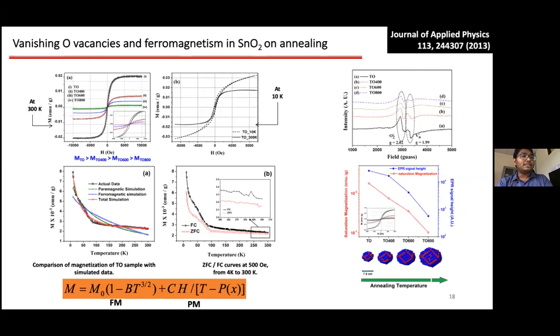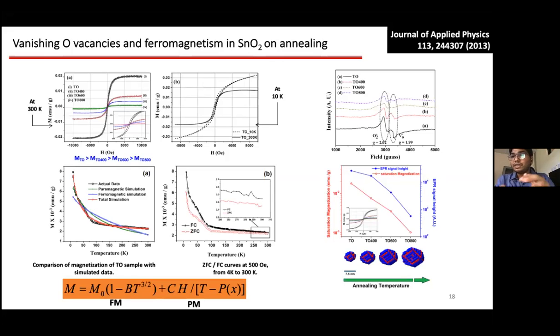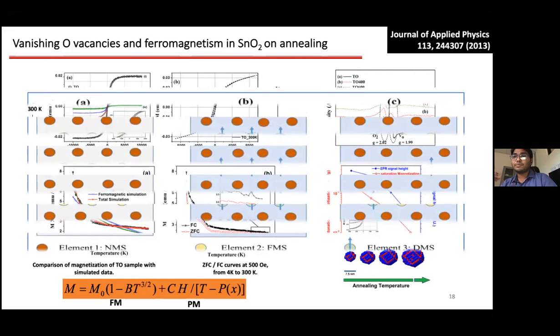Then we did electron paramagnetic resonance on these samples, and people have done DFTs. They have calculated what should be the g value if there is an unpaired spin in the vacancy site. So these vacancies can actually work like trap states. They can trap a single electron, they can trap two electrons. So when it traps a single electron, it is paramagnetic.